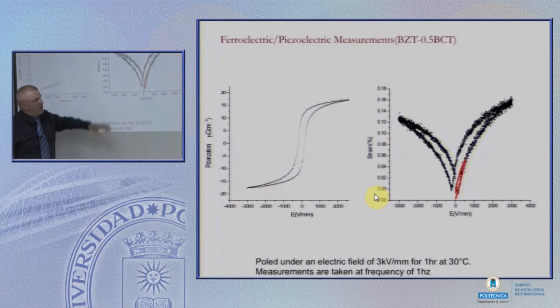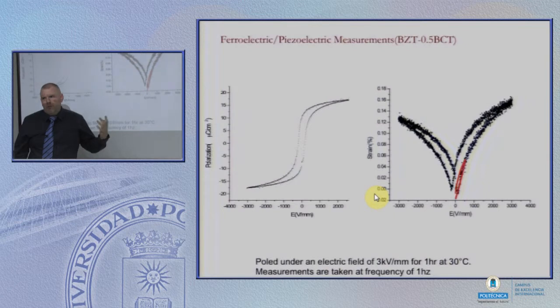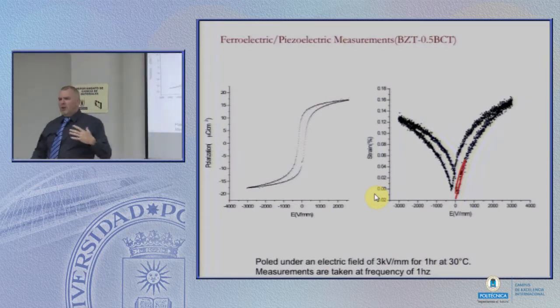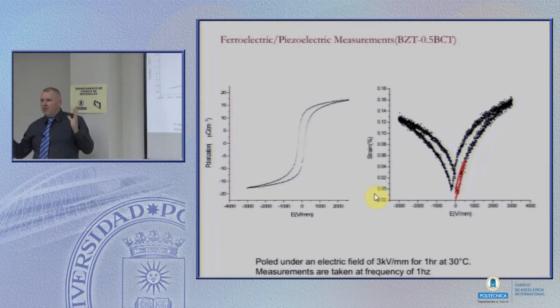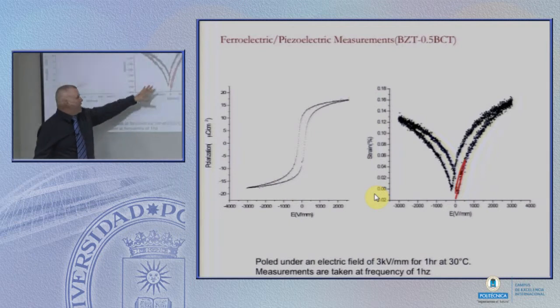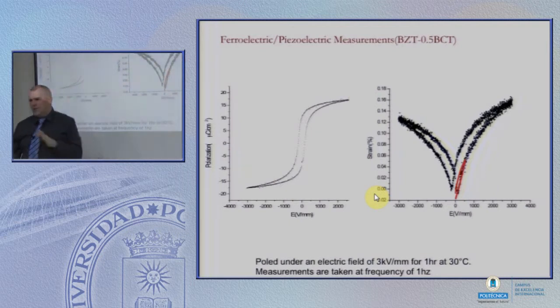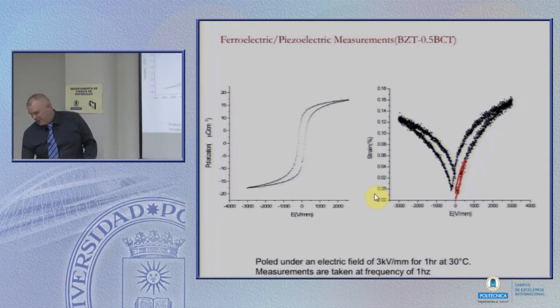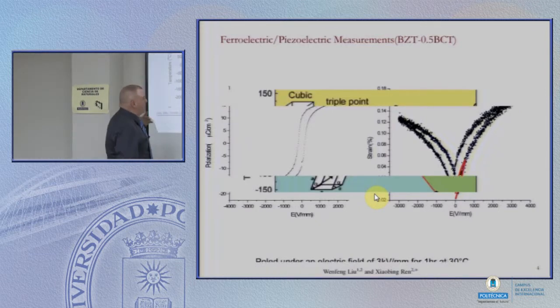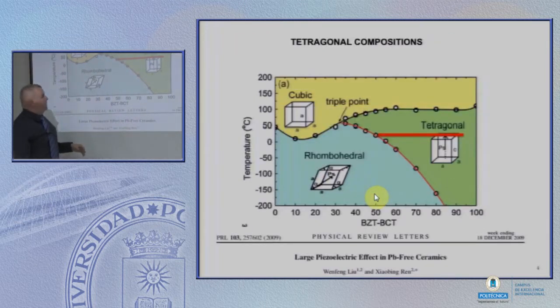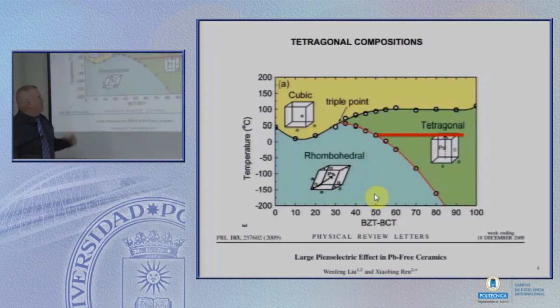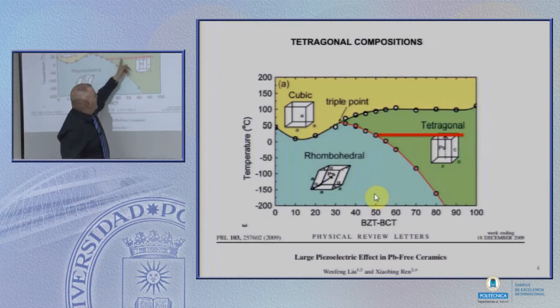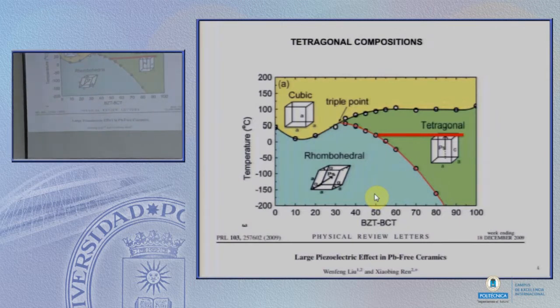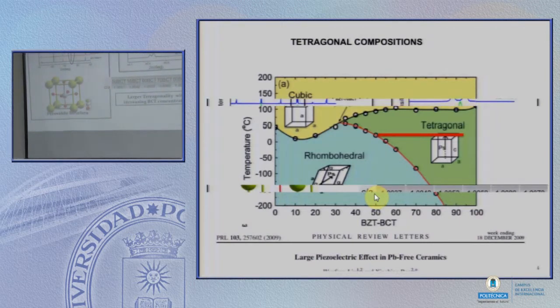Often the strain loops for piezoelectric materials, in the most classic viewpoint, look a little bit like butterflies, right? In this case, for the conditions we used, for the composition, for everything else, they actually look a little bit more like seagulls. So, seagulls versus butterflies. But we did an investigation. Binjin Li did a master's degree for us, and he explored the tetragonal materials. And so we did compositions all the way across here, right? And I'm going to show you those results all encapsulated in one set of views.